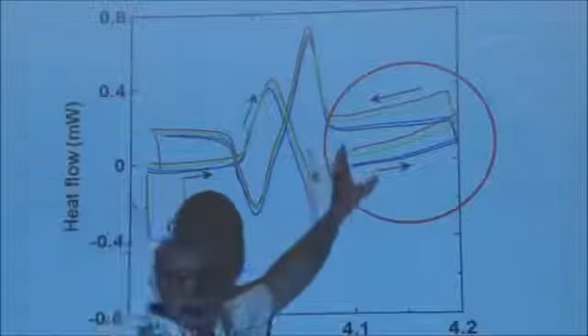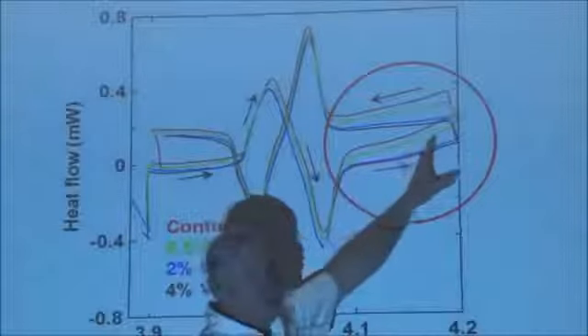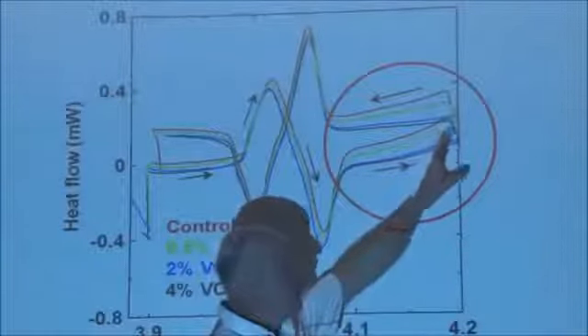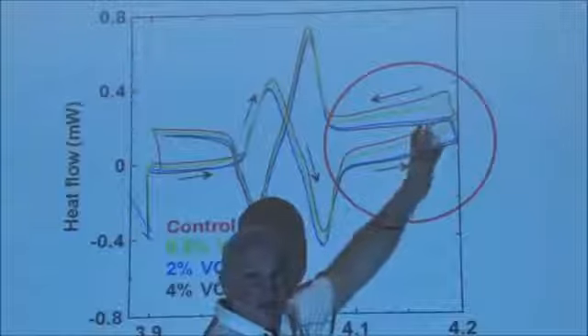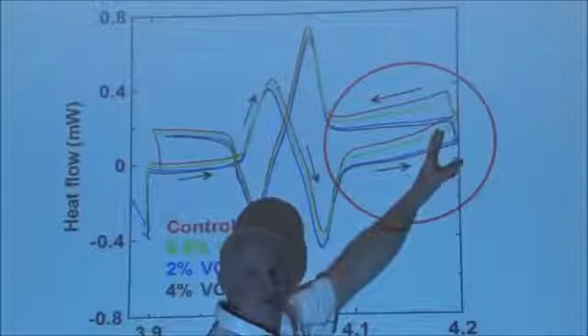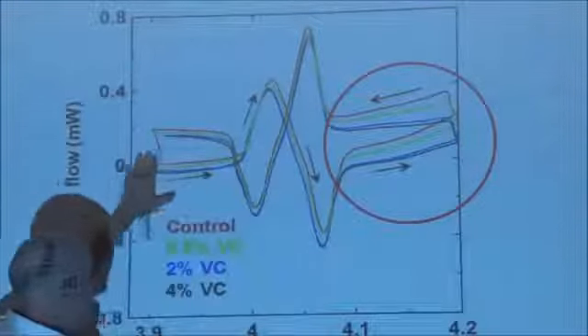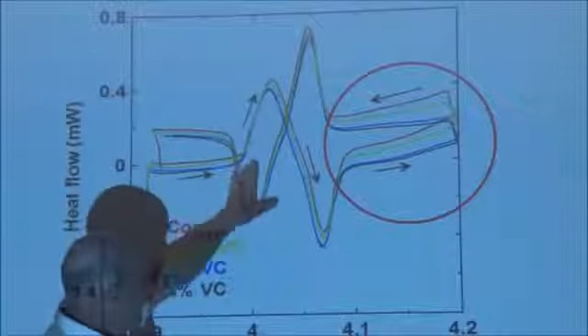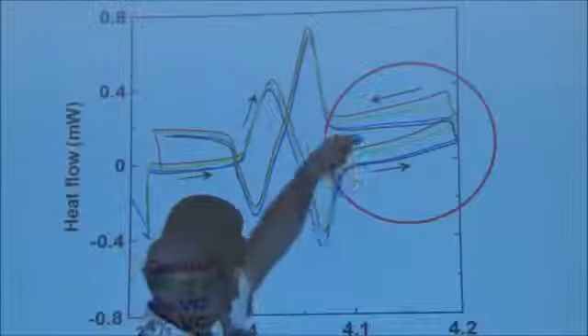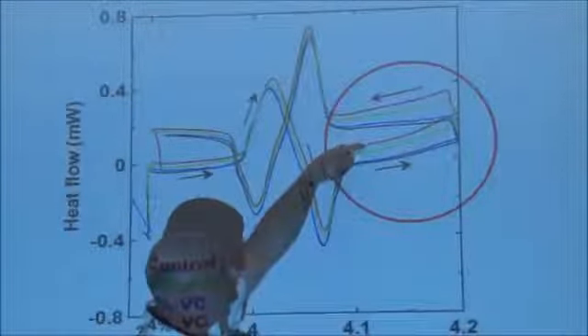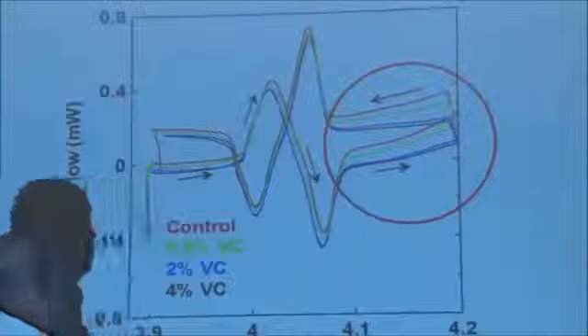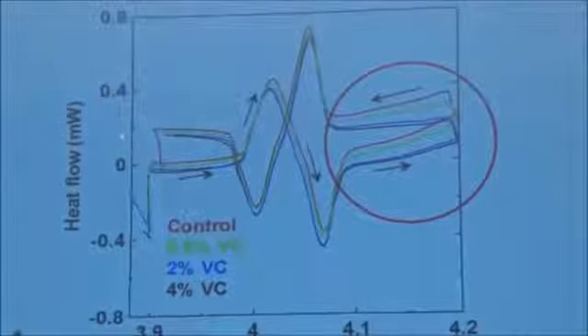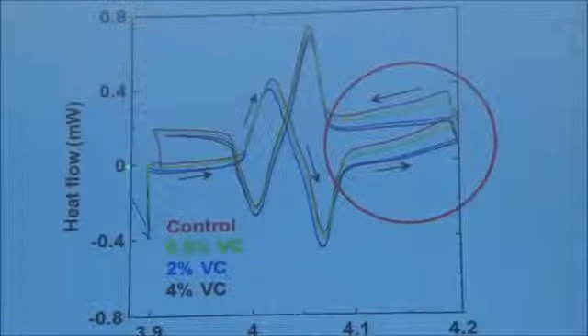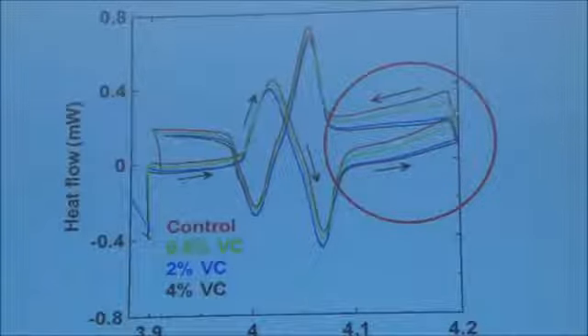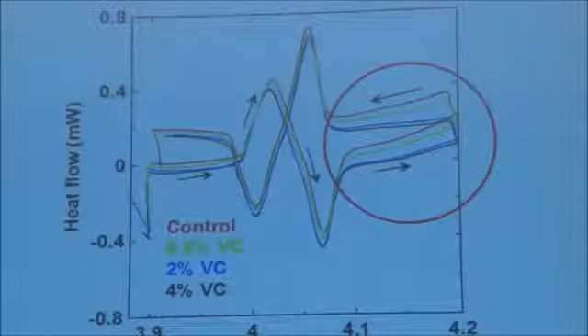So the vinylene carbonate is suppressing parasitic heat due to electrolyte oxidation. We saw that early on from our charge slippage measurements. And you can see that at voltages above 4.1 volts or so, the impact of vinylene carbonate starts to get very important. Look at the scale. From that tick mark to that is 200 microwatts. So it's suppressing things by on the order of 100 microwatts.